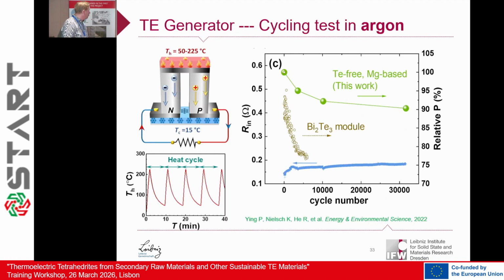Then comes the important factor, magnesium. There are some instabilities and so on. How can we deal with it in terms of cycling tests? We did some rather harsh treatment of these modules. So we treated them, I think, a bit harsher than bismuth telluride modules. We heat up these modules on one side to more than 200 centigrade. Then we let them cool down. The heat up takes roughly 1 minute. The cool down is about 9 minutes. So one cycle is typically 10 minutes.